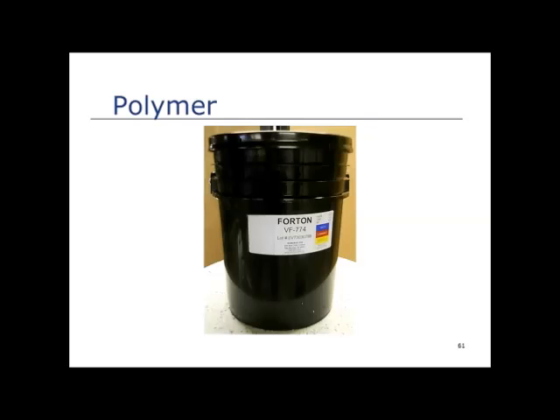So, question: I have a lot of foaming issues with wet casting GFRC over a mist coat. The foam basically separates and rises to the top, and this leaves a layer that has a lot of holes and causes problems. Can you go through what might be causing this and how to avoid it? Well, it really depends on what polymer you're using. Are you using a defoamer? It could be that you're getting segregation.